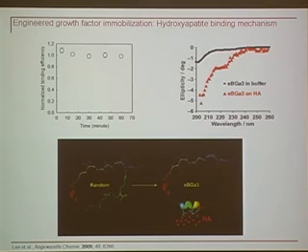If we look at the circular dichroism spectrum of these molecules in the absence or in the presence of hydroxyapatite particles, we see this kind of difference. The EBGA3 peptide in solution, just in buffer, looks like a random coil. If we then add hydroxyapatite particles, you see development of peaks at 208 and 222 that are typically associated with alpha helix structure.